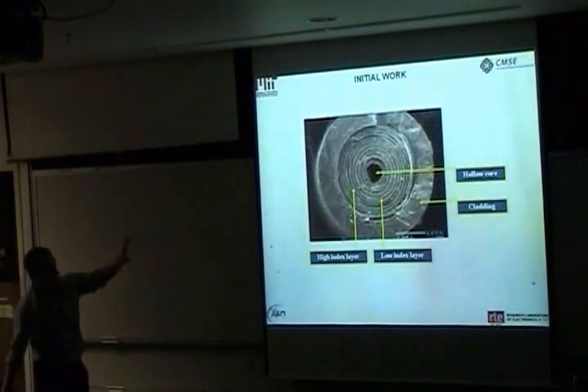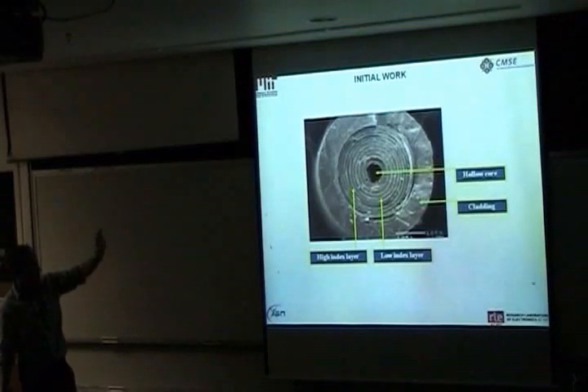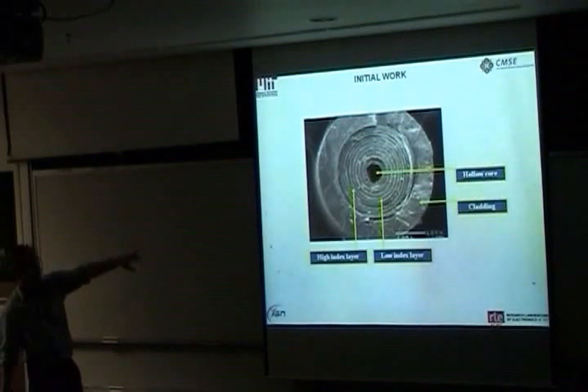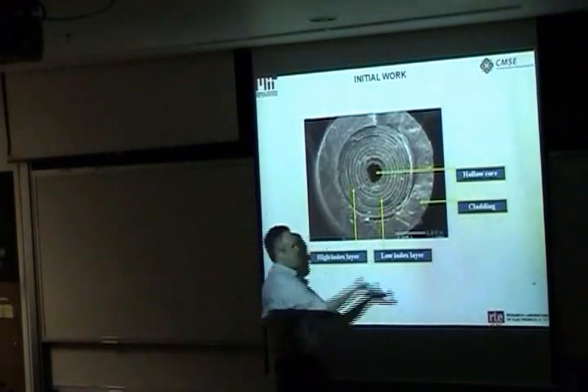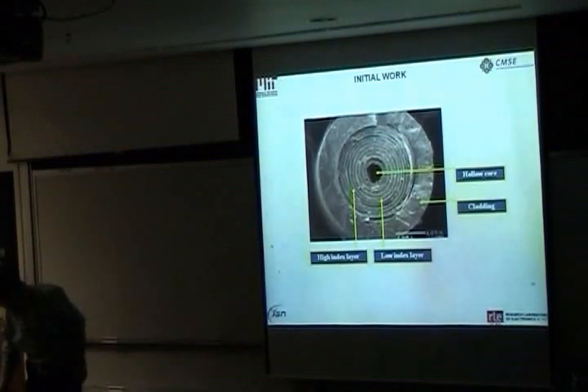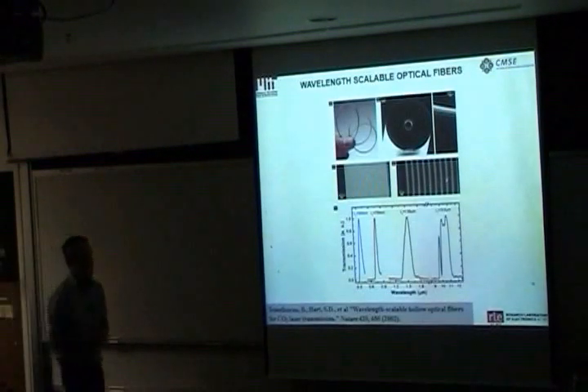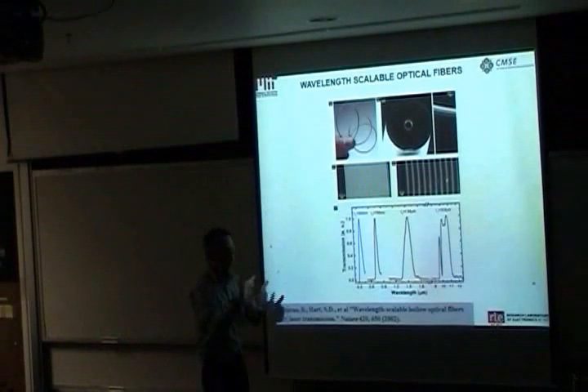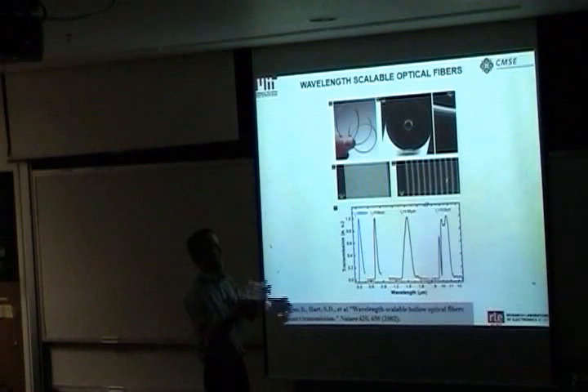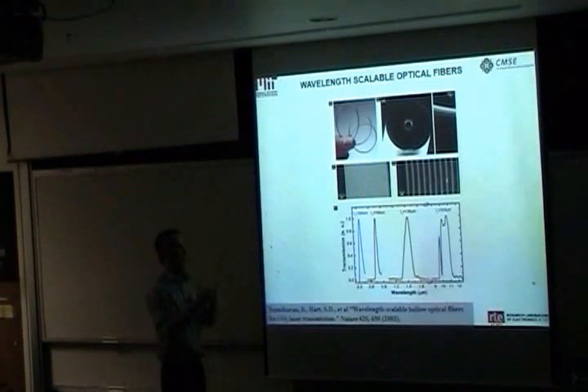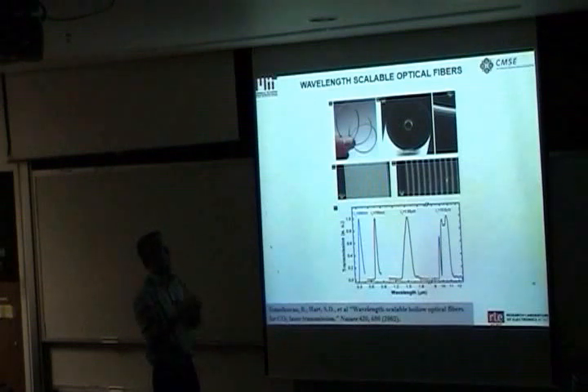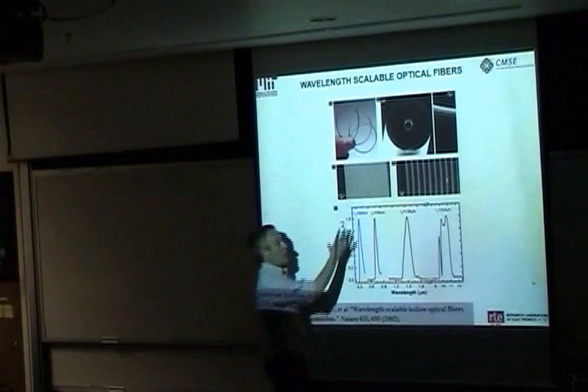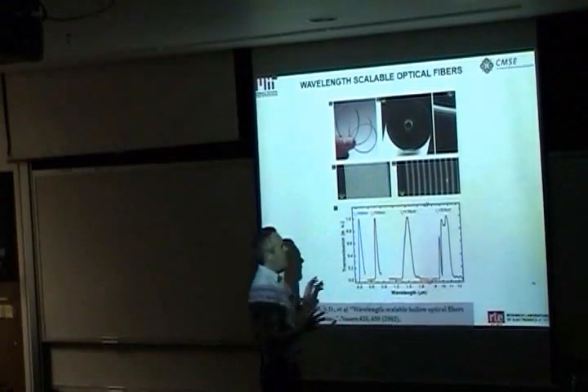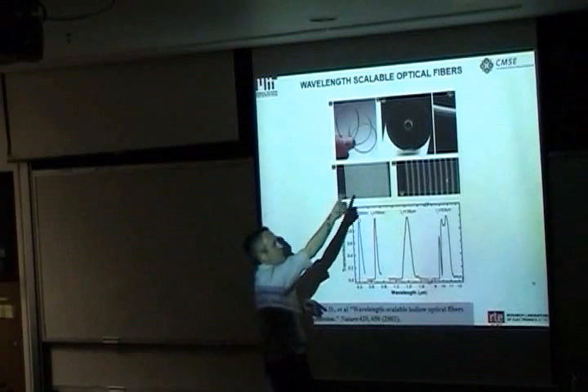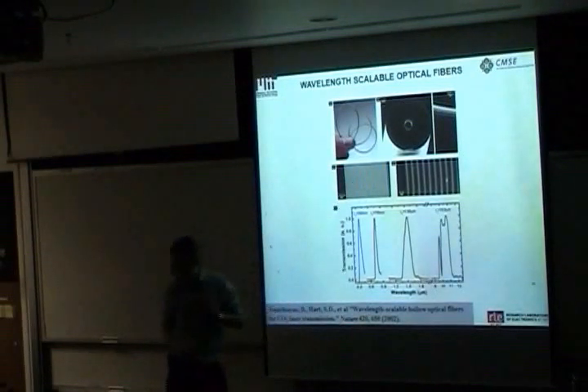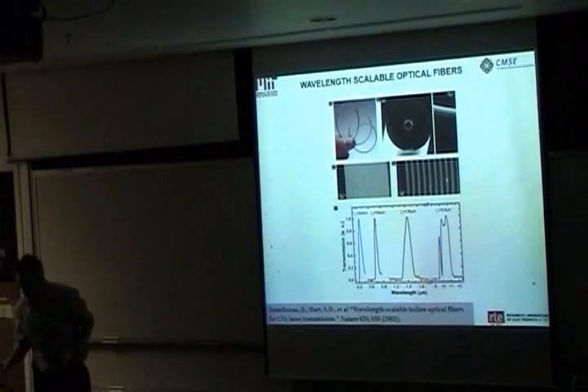And then we got a little better at this, and at least we could maintain a core, but this is a very large structure, the layers here are about 20 microns or 30 microns, and this could work for some very long terahertz waves. And then eventually one focuses and goes through an iterative process and studies all the failure modes and realizes that gas has to be evacuated and consolidation has to happen, and you have to actually dry out the polymer sheets very well, and so on and so forth. And eventually you reach these types of structures over here. And this is what a fiber looks like today. So you see the hollow core over here, and where's the pointer at? It's hidden. Thank you.